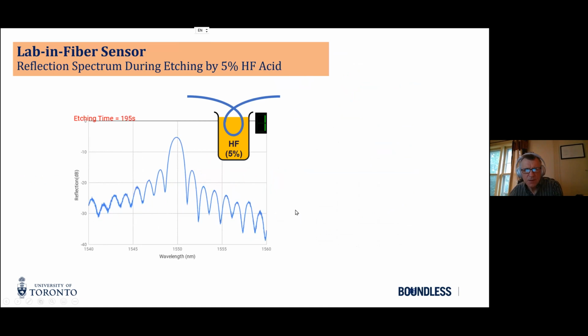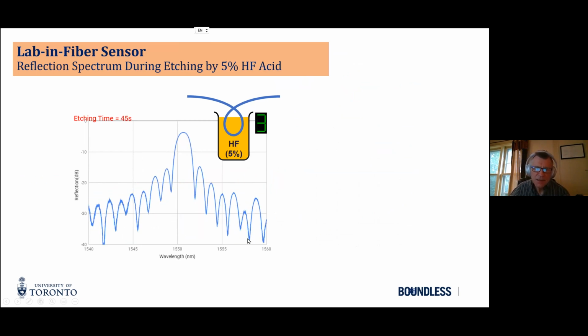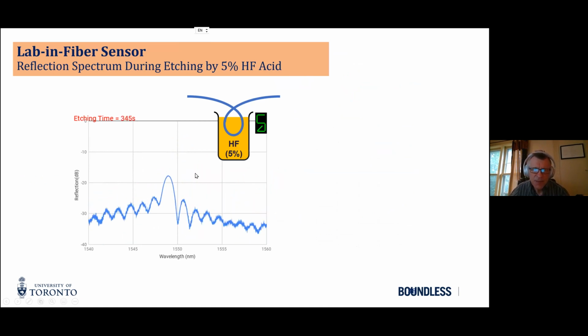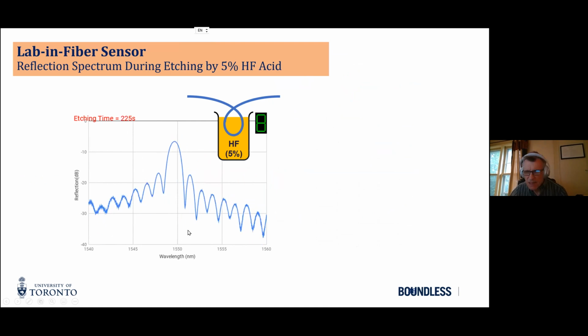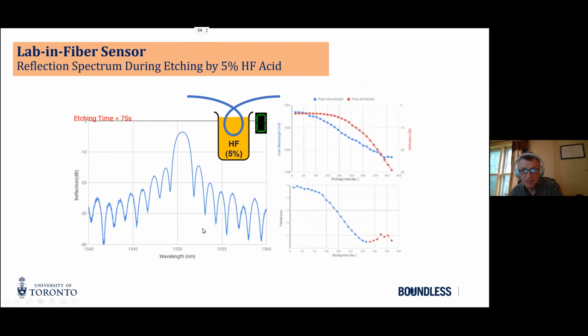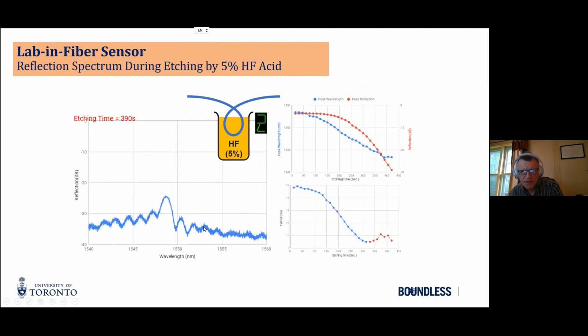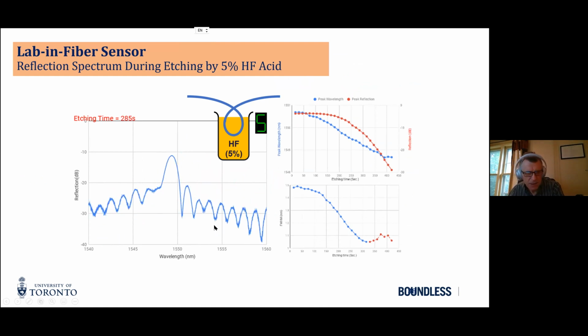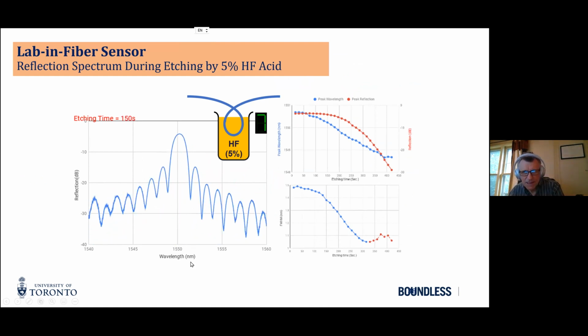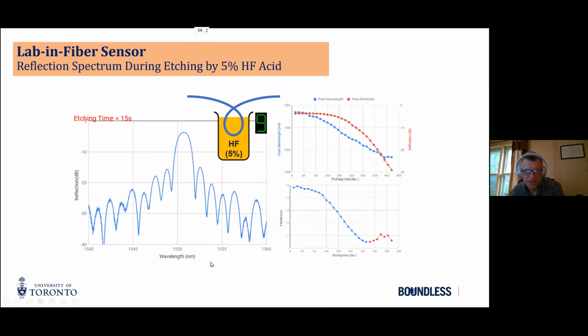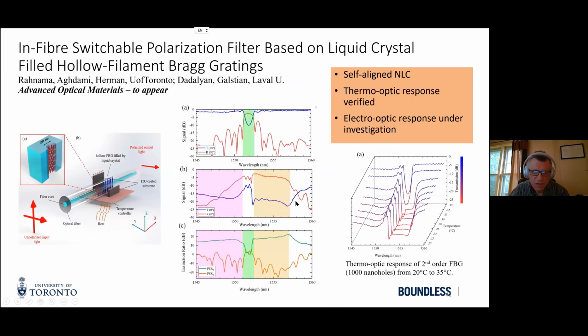And you can also, with weak acid, tune the holes, and these are stop band shifts with time as hole diameters increase up to 700 nanometers. So we've really characterized this, and we have a paper in review at Nature Communications on this topic. Here's a paper also just almost ready to appear now in Advanced Optical Materials.